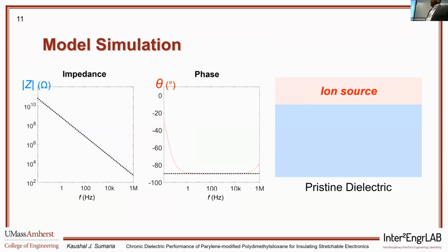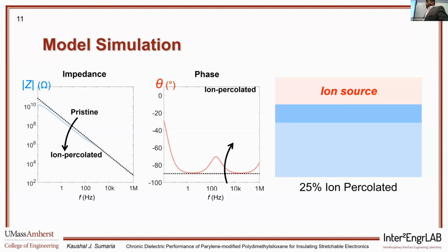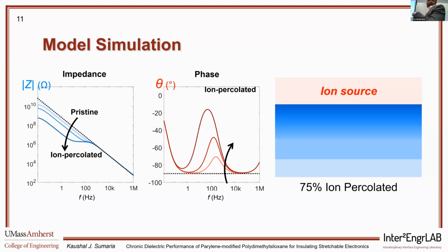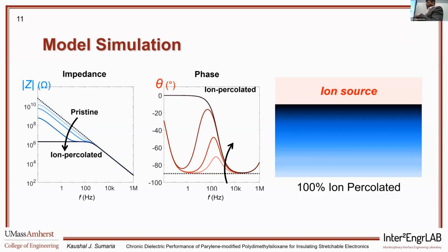So if you look at the ideal dielectric or a capacitor, that would look like a dashed line shown here with the phase plot at -90 degrees. Our dielectric that is simulated shows similar properties when it is free of any ions. Once more and more ions are percolated inside the dielectric, we see that the impedance has a shift, and then ultimately it flattens out. Physically, that means that at that point, instead of showing a dielectric property, the dielectric layer is actually showing resistive properties, and the flat line should be a summation of the resistance from the solution plus the resistance of the dielectric material already percolated with ions.